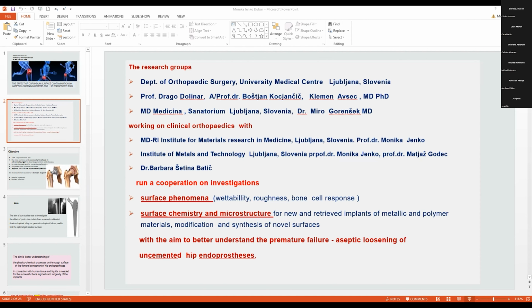Then we use X-ray photoelectron spectroscopy for surface analysis and time-of-flight secondary ion mass spectrometry of the thin oxide film on the rough surface. But in fact, we can study this passive film only on a polished surface. It is not possible to use such sensitive methods like X-ray photoelectron and time-of-flight SIMS for analysis of such a rough surface.